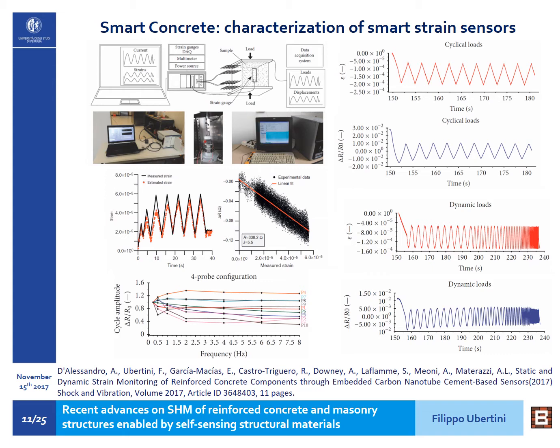You clearly see that there is a very good correspondence between strain and electrical response, which is also the case on the bottom right when applying dynamic loads, so sinusoidal loads with increasing frequency. On the left you see the strain measured by strain gauges in a typical test with triangular loads, as well as the strain estimated by using the electrical output from a smart concrete sensor in red. And you also see that the relationship between change in resistance and strain is actually linear, very much linear, as we assume in a very simplified model.